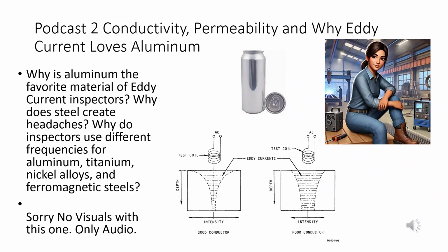The inspector's thought process. Experienced inspectors don't start by asking, what frequency should I use? They start by asking, what material am I inspecting? What is its conductivity? What is its permeability? How deep is the flaw? What signal-to-noise ratio do I need? Then frequency selection follows. The big picture: conductivity controls how strongly eddy currents form. Permeability controls how magnetic fields behave. Together they determine signal strength, penetration depth, frequency selection, inspection difficulty, interpretation difficulty, everything.